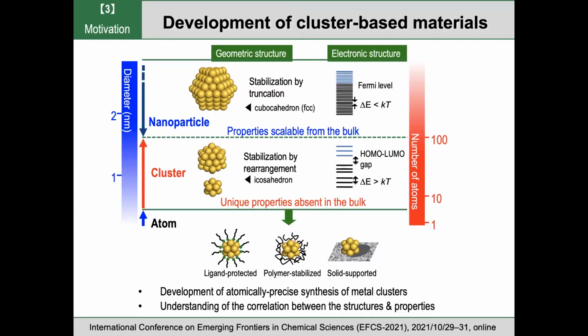But if you go smaller, below 2 nanometers or less than 100 atoms, the situation changes dramatically. In the case of clusters, atomic packing is quite different from bulk metals. For example, they can form icosahedral packing, which has 5-fold symmetry. This packing cannot be achieved in the bulk. Also, the electronic structures of such small clusters are well quantized, so basically they are not metal anymore. So we can expect some unusual properties in such a small regime.